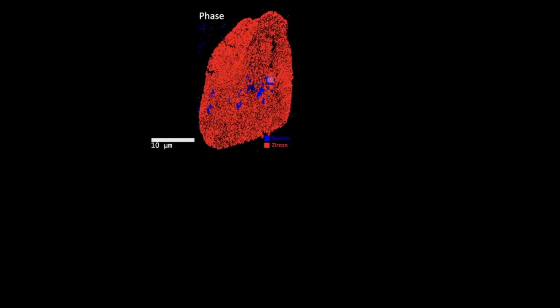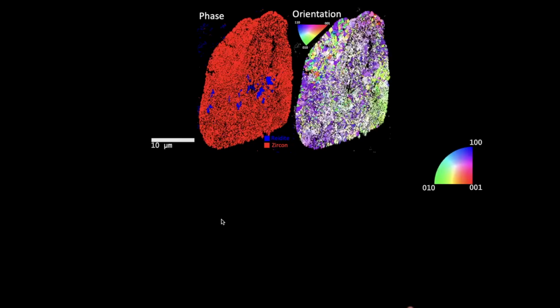This one actually indexed as Reidite in a lot of the center here. These could be remnants. They could be granular Reidite. They could be remnants of lamellae. I'm not really sure, and I don't think we can really tell. But that's interesting because we did see that in the backscatter electron imaging. So you can already see that these two grains, while they have the same systematically oriented granular zircon microstructure, they're obviously not completely the same.